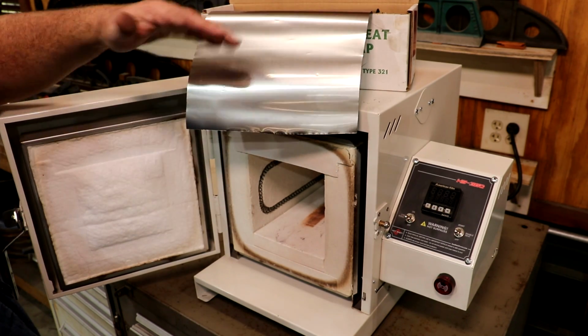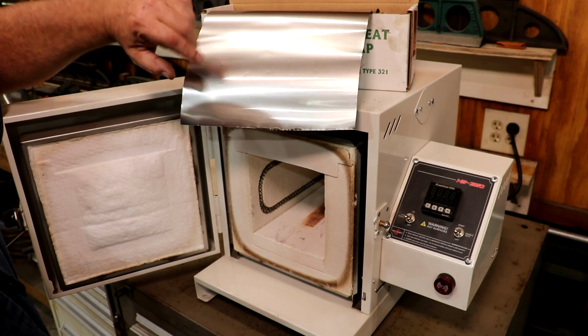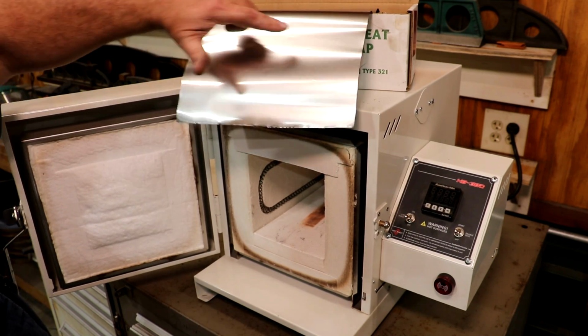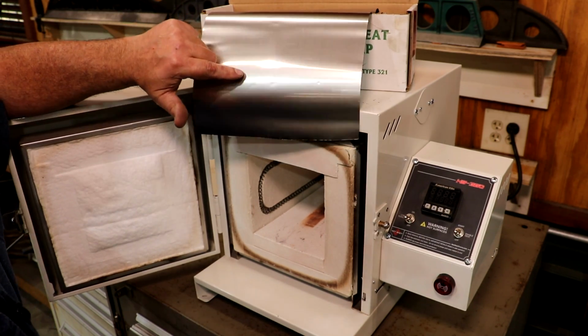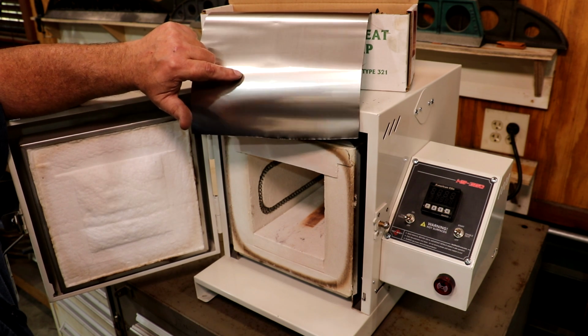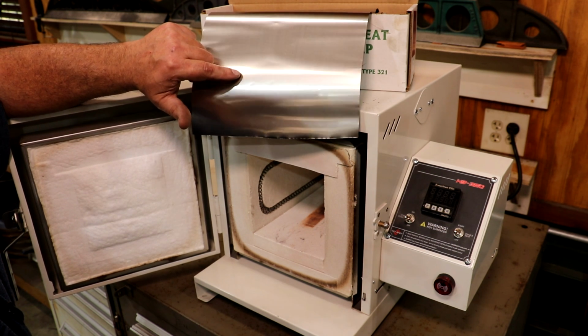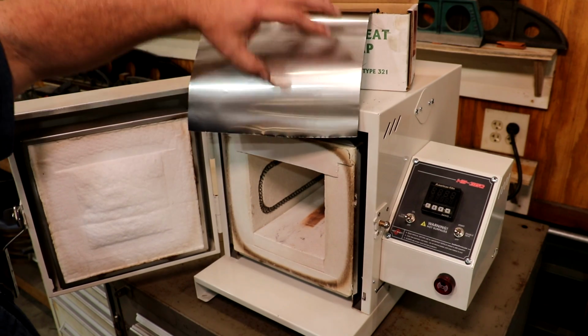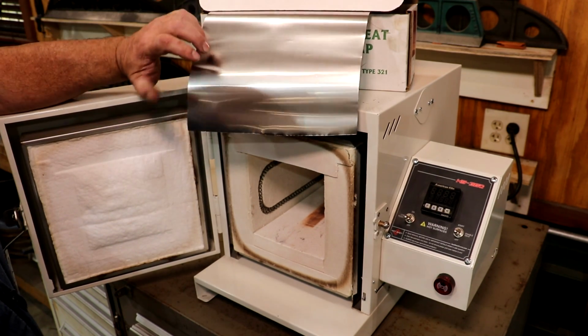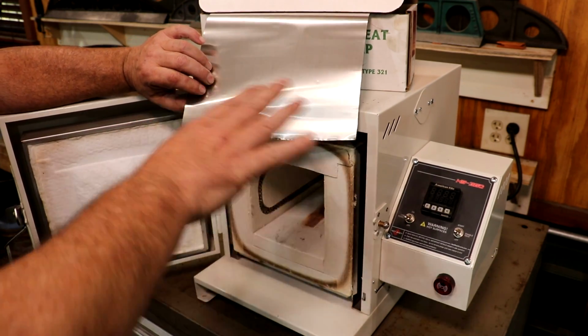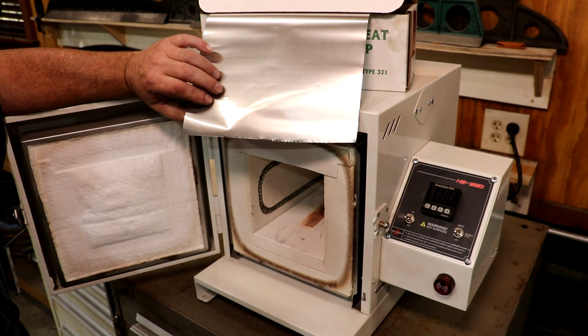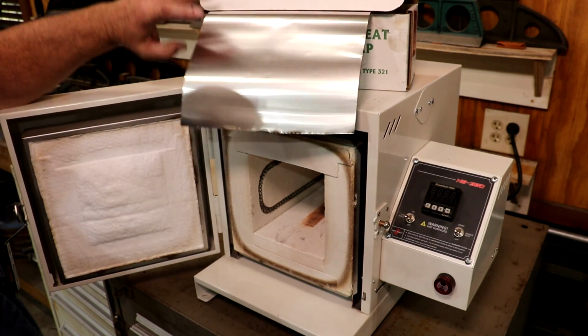But you wrap your part up in it tightly, fold your corners up, seal it up real good. I usually put a little tiny strip of paper inside of that so that when it gets to the temperature that it'll start burning, it will burn that paper, and any oxygen that is inside this foil will be consumed as that paper burns away before it ever causes any problems on your part.